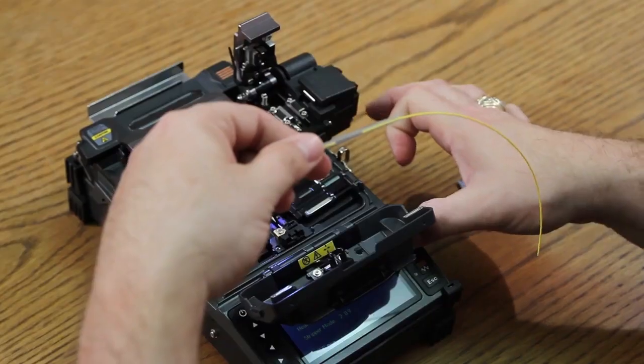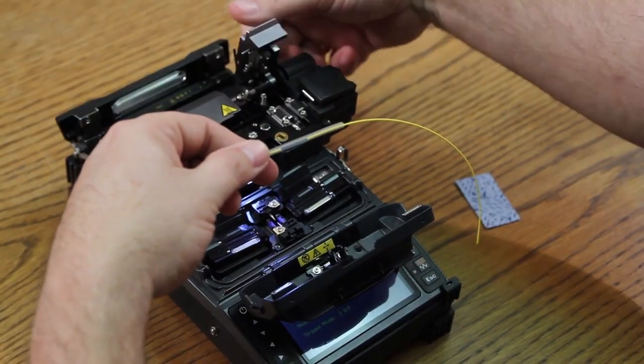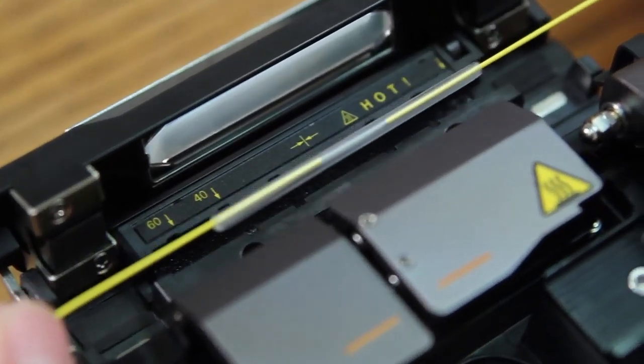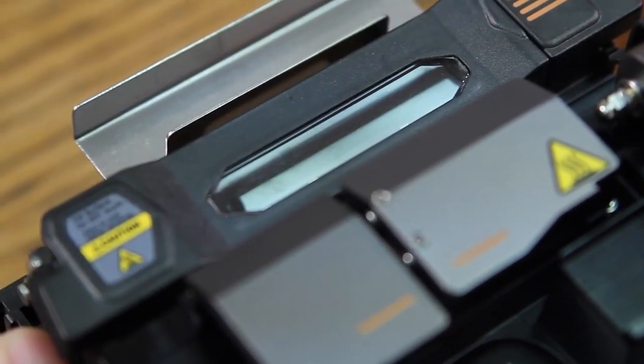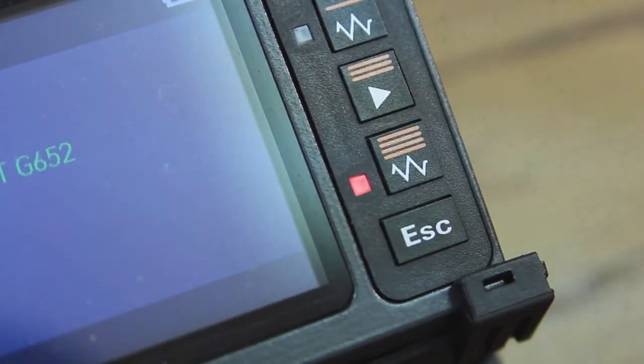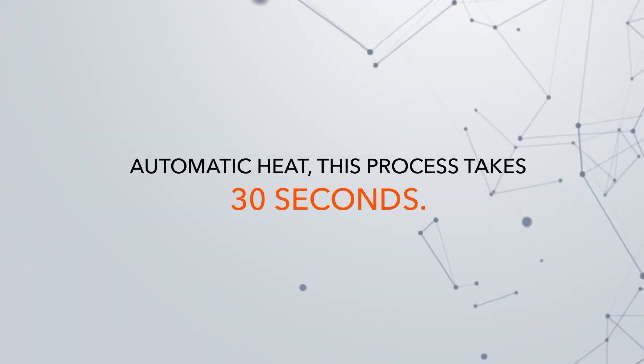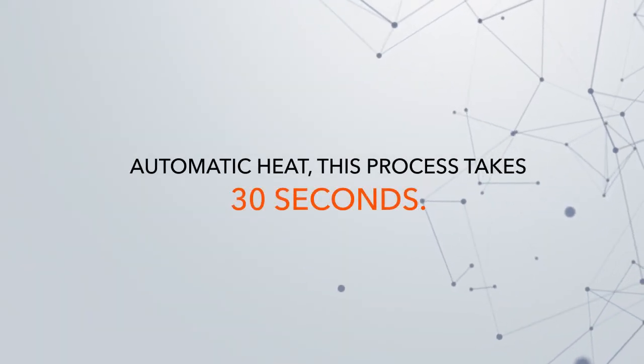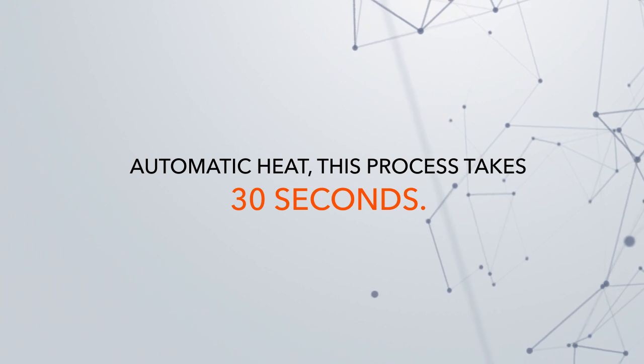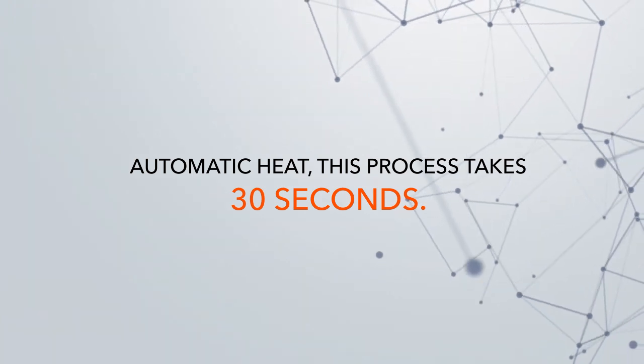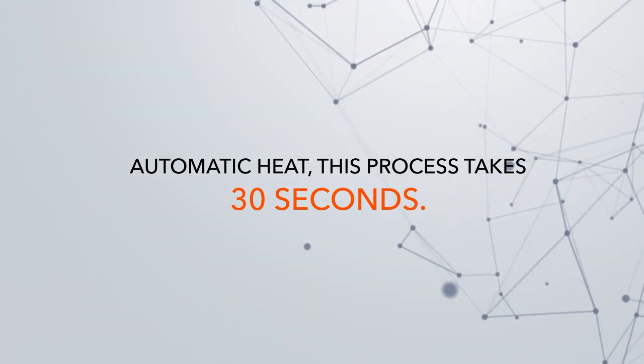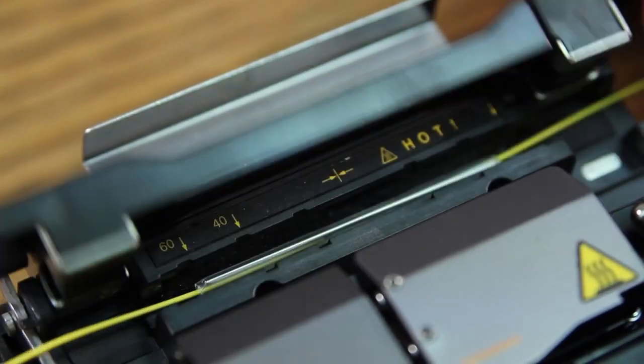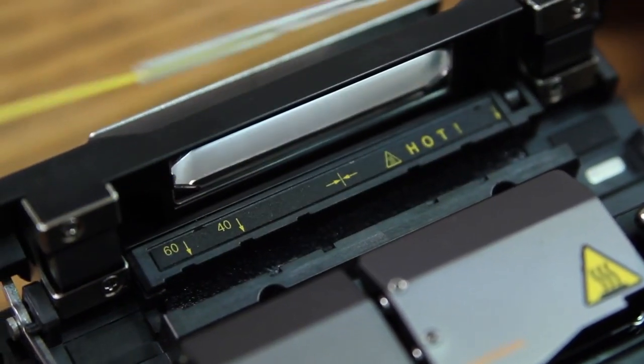Then slide your heat shrink sleeve and open your oven. Insert into your oven and close the doors. Turn your oven on. You can set the oven to an automatic heat, so when the door closes, it will automatically turn on. This process takes about 30 seconds. When complete, move your fiber and place into your cooling tray.